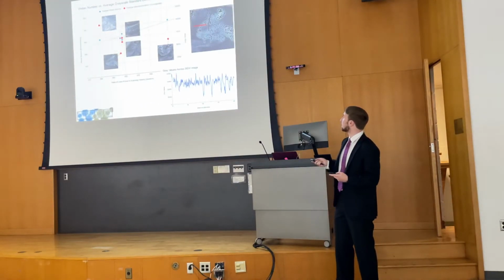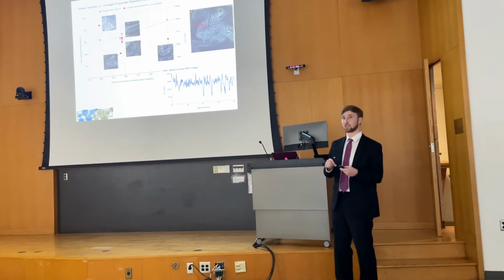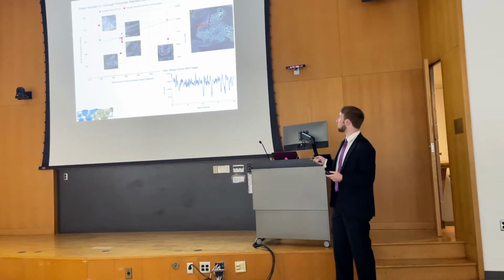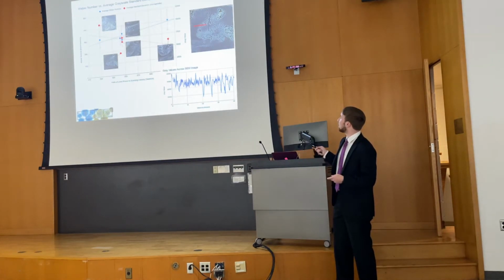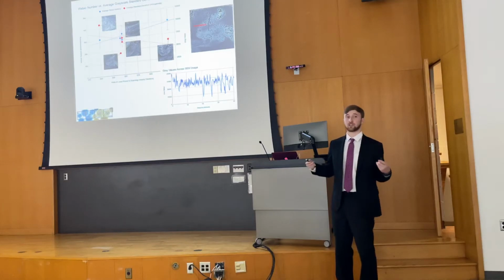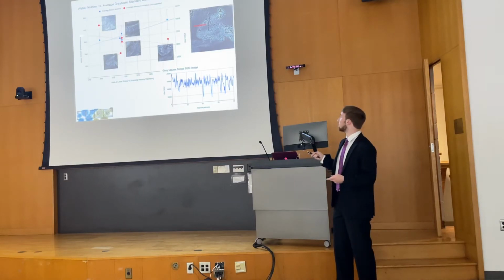The first was looking at the standard deviation, because when it was more consistent with a single gray value, the standard deviation would account for more homogeneity of the data itself. So in a scan like this, you would have something like that. And the standard deviation was averaged across a number of scans across a number of pictures. And we found this trend that showed that a higher Weber number, which you'll remember is increasing turbulence within the melt pool, led to better homogeneity as a lower standard deviation of these grayscale values.